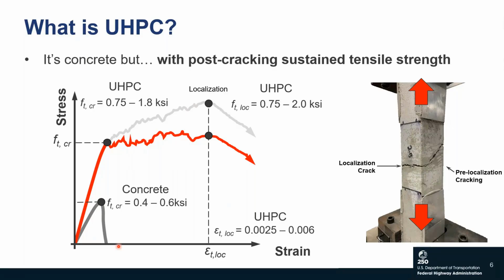However, take a stick of UHPC and you start pulling on it, you'll get the stress strain curve I'm showing here on the screen. UHPC has fibers in it, and those fibers bridge that first crack. So it stops that crack from growing, reinforces it at that location, and then another crack will form. The fibers over there also reinforce that crack, stop it from growing, then another will form. And then you enter what we call a multiple cracking phase, where multiple cracks are forming and being bridged. And those cracks are very, very small. You can't really see them with the naked eye.